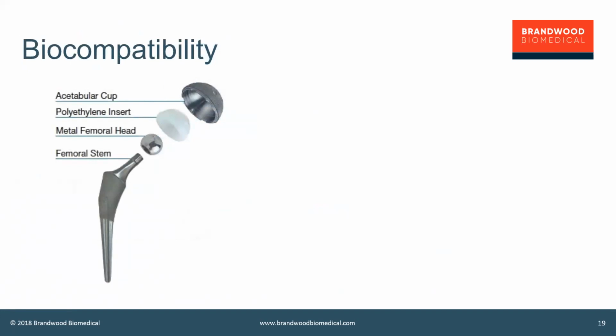And if you go to the standards that describe these surgical alloys, ASTM standards for things like surgical titanium or for cobalt chrome, will all contain a passage that says these devices, if they are appropriately clean and appropriately processed, are considered to be biocompatible. These materials have an established record of biocompatibility, and you don't need to go off and yet again test surgical steel. You don't need to go off and test yet again titanium vanadium alloy. You shouldn't be needing to go off and test nitinol, providing you can show that your manufacturing process doesn't add anything else, that you don't contaminate the metal in the processing. That's fine. So these are mass-produced devices produced by forging, machining, whatever, and the materials are very well understood.